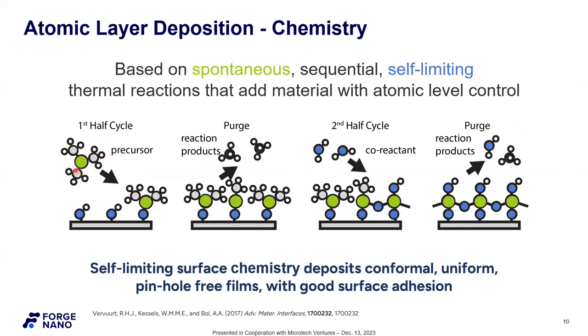Okay, so now our green Lego block is trimethyl aluminum, or TMA. Aluminum is green in the middle, and it's surrounded by CH3 or methyl groups. When this sees the surface of hydroxyl groups, or OH, you move a proton, an H, from the surface to the CH3, and you make methane. Great, that goes away. More importantly, you make a surface oxygen-aluminum bond. And as I've already mentioned, this is where that great surface adhesion comes from. By definition, ALD is making and breaking surface bonds. So now you have a very strong, very well adhered film to your surface.